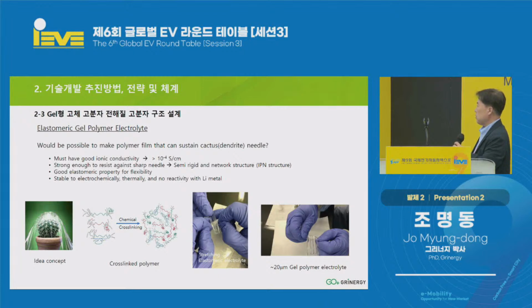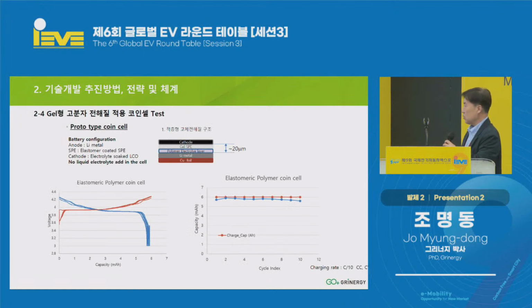So what you are looking at right now is the synthesized films. We couldn't test it on top of the cactus, but we were able to do the testing, and we came to the conclusion that dendrite can be suppressed. So simplistically, these are the tests that we've done. A solid polyelectrolyte application coin cell test was done. Of course, our research is in an early stage, but we are enjoying quite a bit of success, and our research is ongoing. Here, we don't use liquid electrolyte, and we use low molecules, additives and high polymer so that we can create the electrolyte.